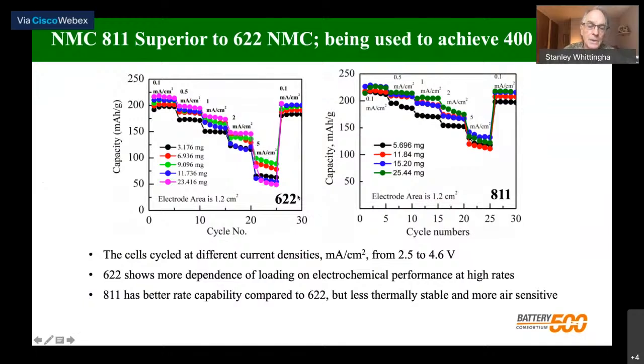So as I said, we use 60% nickel. If we want to go to higher energy densities, we've got to use more nickel. So we investigated going to 80% nickel. Don't worry about all the details in here. Basically, this is the lowest current we use. That's the lowest chemical reaction rate. Towards the right, we now have a much higher current. And you can see as we increase the current, the capacity drops down here.